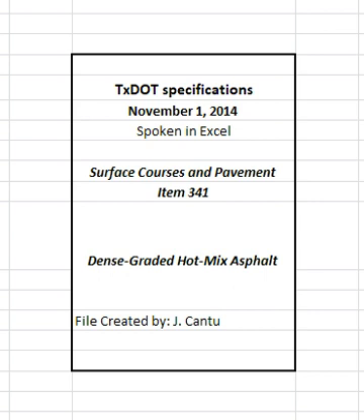2.8 Substitute binders. Unless otherwise shown on the plans, the contractor may use a substitute PG binder listed in Table 5 instead of the PG binder originally specified, if the substitute PG binder and mixture made with the substitute PG binder meet the following. The substitute binder meets the specification requirements for the substitute binder grade in accordance with Section 300.2.10, Performance-Graded Binders, and the mixture has less than 10.0 mm of rutting on the Hamburg wheel test, Tex-242-F, after the number of passes required for the originally specified binder.